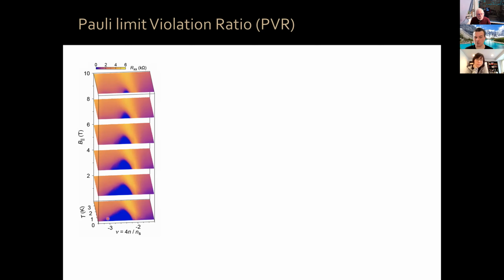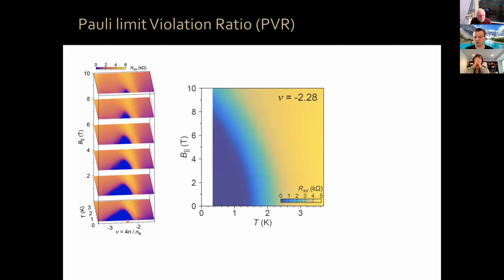This is the usual superconducting dome, doping and temperature. And we can do this at different parallel magnetic fields. You can see again that at 10 Tesla, we still have a finite superconducting dome, okay? Now I can take a particular density, filling factor, and measure continuously your resistivity. The resistivity is a function of temperature and parallel magnetic field, okay? You can see this here.